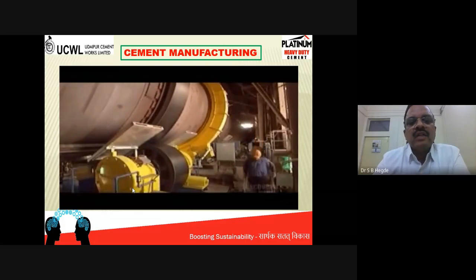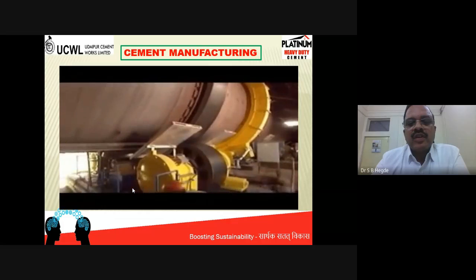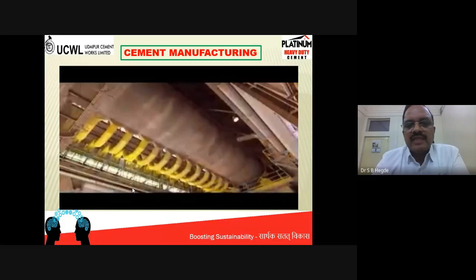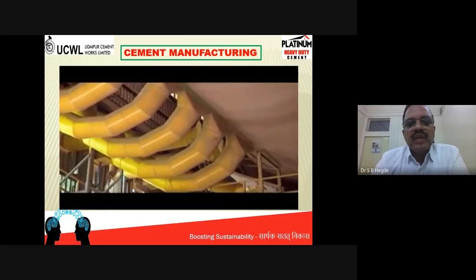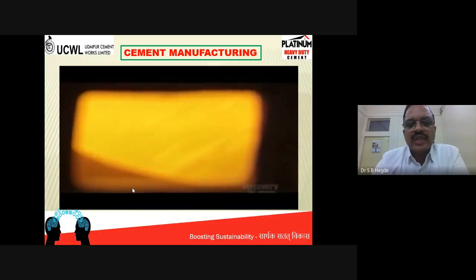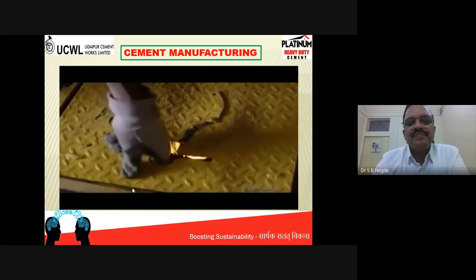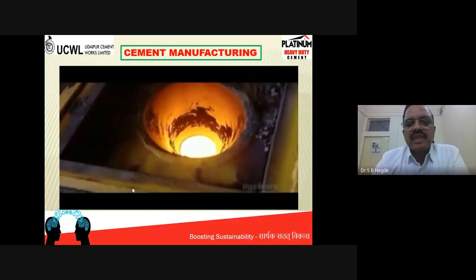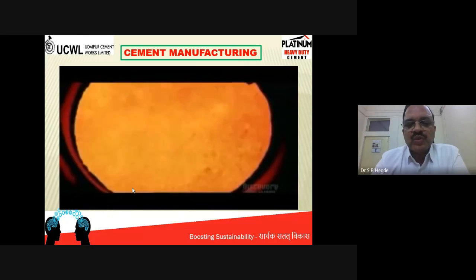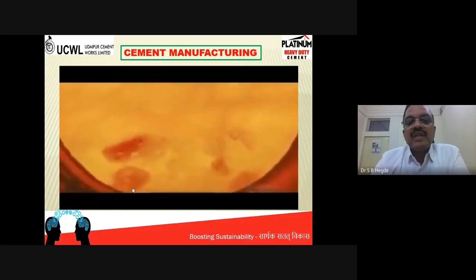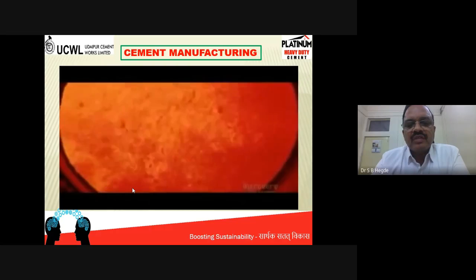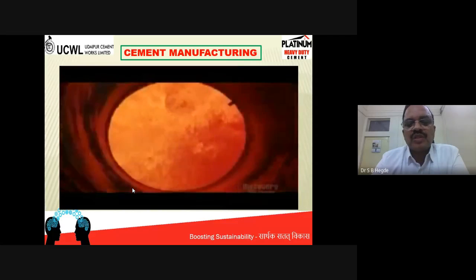You can see the rotary kiln which is under operation. Inside this there will be 1450 degrees centigrade, and all these materials will be converted into a boulder-type material called clinker. This is the view of the burning zone inside the kiln. This hot material will be sent to the cooler where it will be quenched from 1450 degrees centigrade to around 1000 or 800 degrees centigrade.